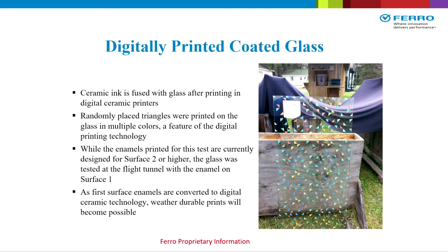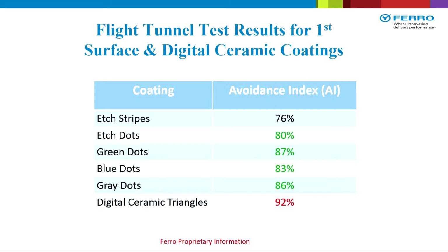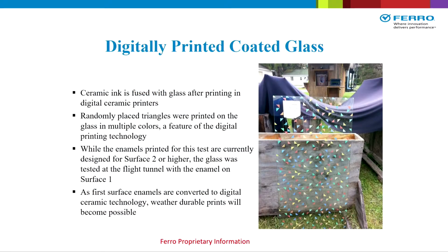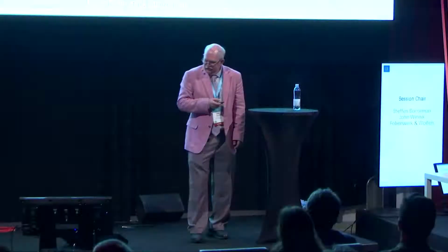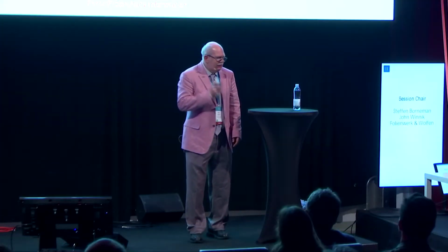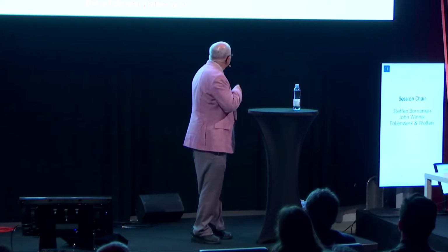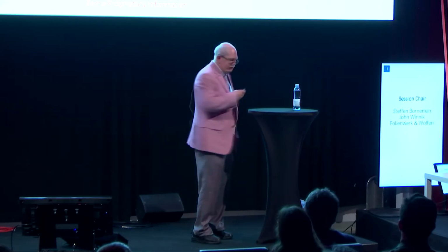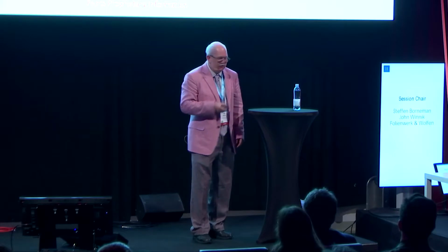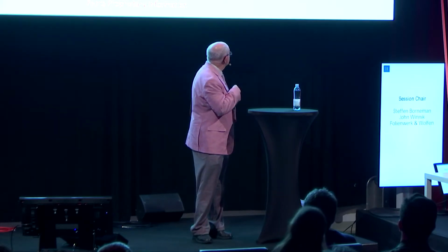So the ceramic ink is fused to the glass after it's printed and dried. And then for this work, we put these randomly colored triangles on the glass in different colors and positions. And so one thing to note about this is that these enamels here are currently designed for the second surface and higher, but in the case of this bird tunnel test, it was tested on the first surface.